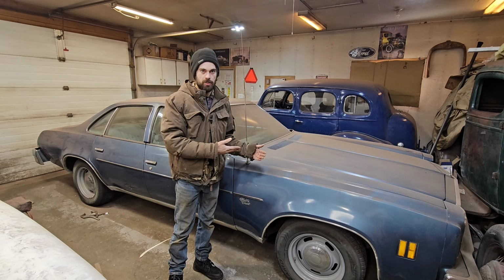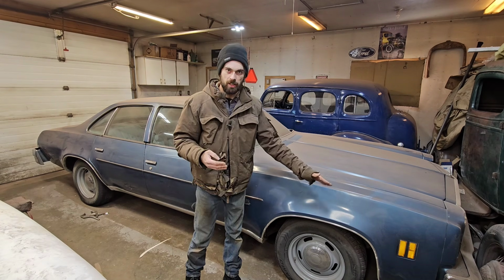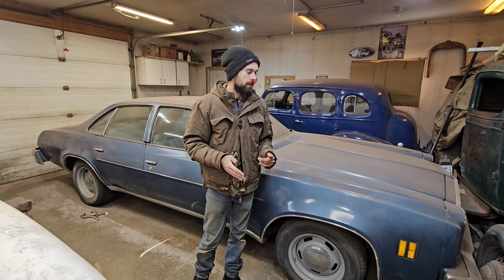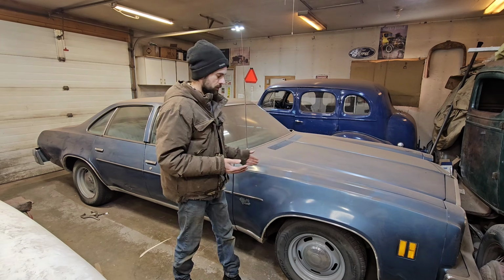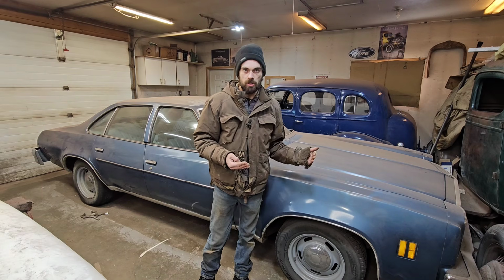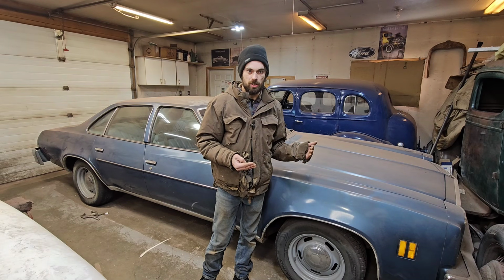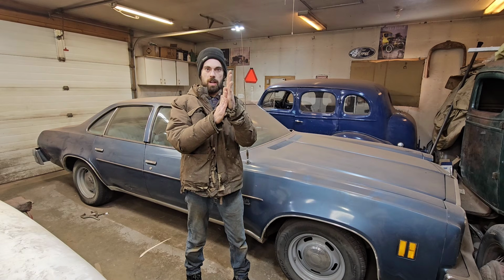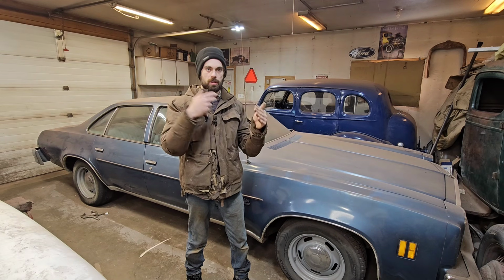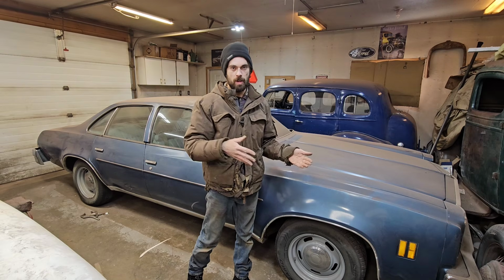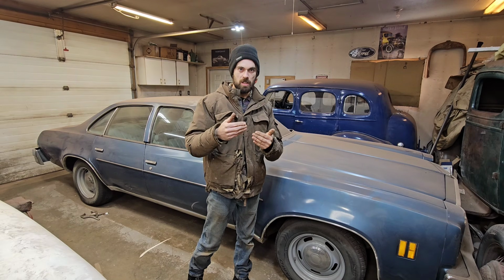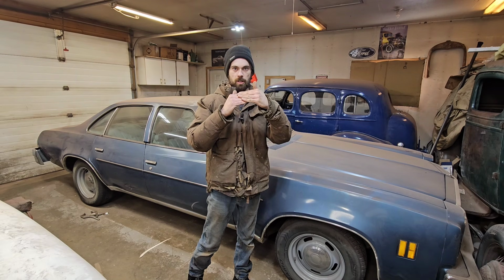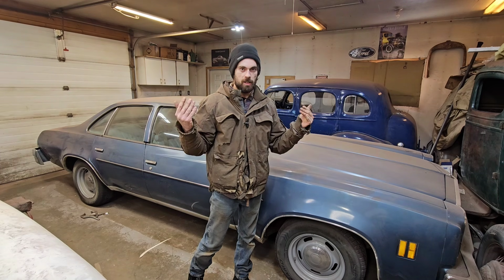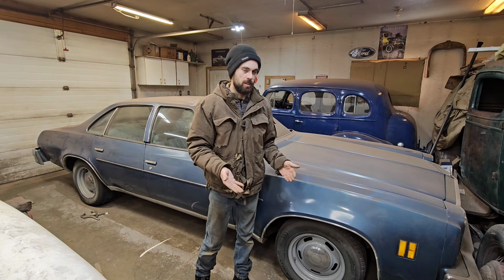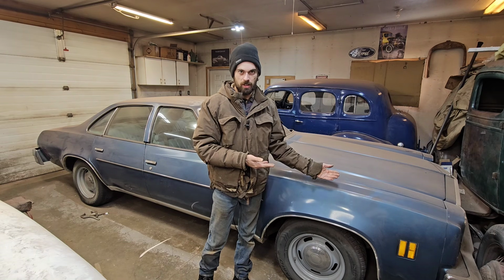Lap weld where the factory does, butt weld if we're joining something in at an area that's not factory. And the reason for that is, again, it allows for an invisible repair. The butt weld also allows for better corrosion protection. That means that with a lap joint, it's difficult to tell whether or not the epoxy and the wax oil has actually made its way into that seam. So it is an area where moisture can collect, and if that's the way the factory did it, well, we just have to do the best we can. But if it's a non-factory seam, then we typically go towards the invisible repair.